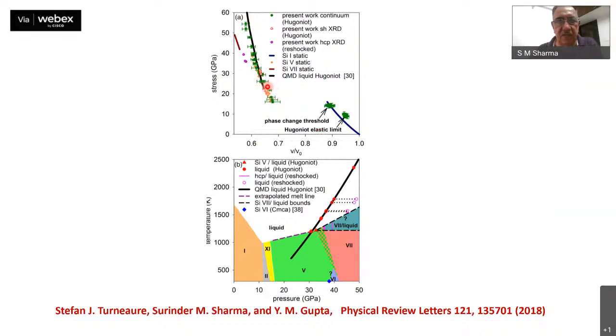These are the ones from the XRD for the primitive hexagonal phase. And see here, it's again matching with the static data. This is after reshock that we get these data points, and this is matching well with the hexagonal close-packed phase data, which is known. Based on what we got, we could construct a phase diagram of silicon. So these are the reshock states. We initially had this state, and after reshock, it went into this state. So when it went into this state, it could go into a crystalline phase, but at much higher stresses, it didn't. So it stayed liquid.